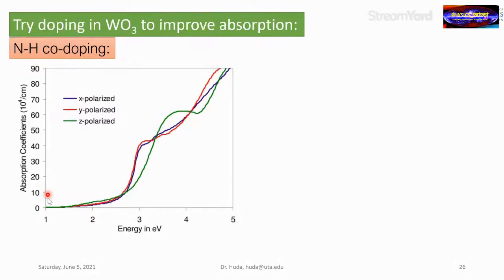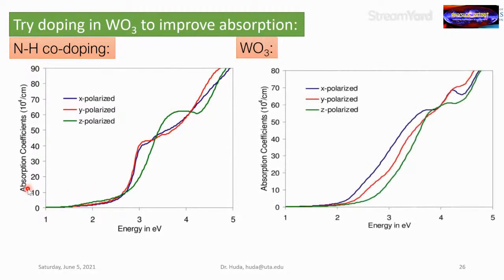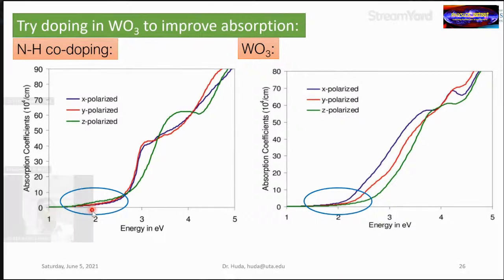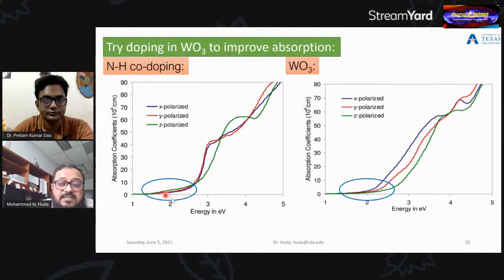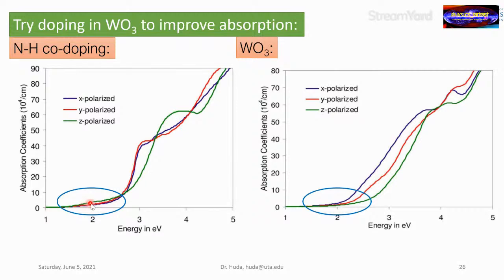Once we do that, we recalculate the absorption coefficient. Now, if I compare with the tungsten oxide, this is the tungsten oxide, around 2 electron volts. If we pay attention, compared to 2 electron volts, with nitrogen doping it increased somehow. Now that increment is not significant enough. It did increase, especially the green line, which is light polarization along the Z direction. That has somewhat more improvement for light absorption. However, the overall improvement is not significant.